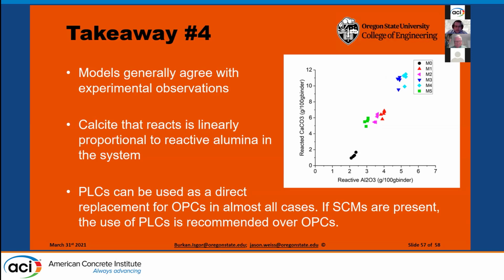So again, the fourth takeaway is that the models are generally agreeing very well with the experimental observation. The calcite that's reacting is directly proportional to the reactive alumina in the system. And all the evidence that we've seen is that PLC can really be used as a direct replacement for the OPC in almost every case.